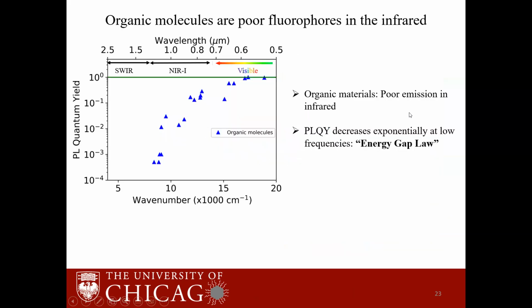Before I go into how to make brighter quantum dots, I want to bring up the question of why are we not considering using organic molecules for deep tissue imaging? So here I have a graph of the quantum yield for organic molecules, including dyes and fluorescent proteins at different wavelengths. So we can see that as we go to longer wavelengths, the quantum yield decreases exponentially. And especially in the shortwave infrared, the quantum yield is extremely poor.